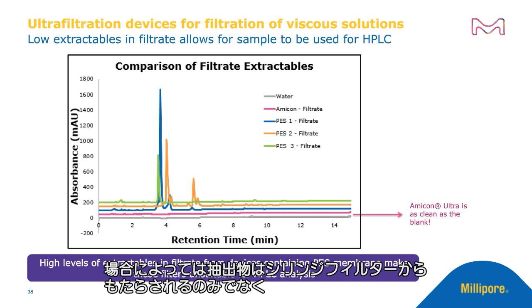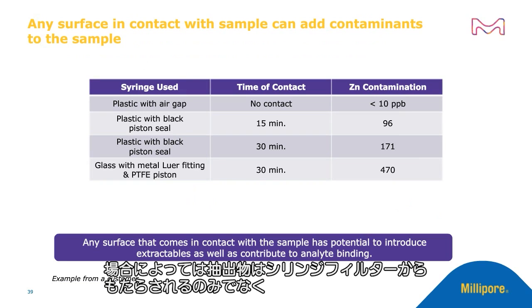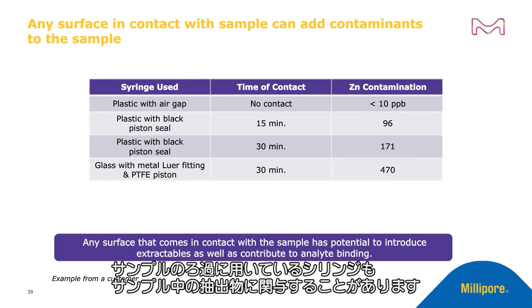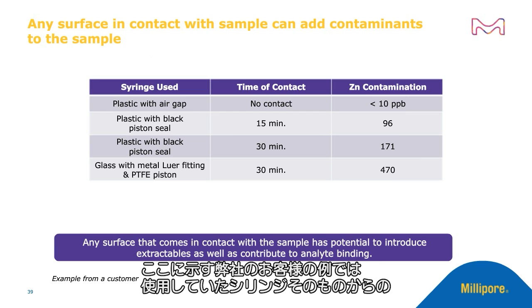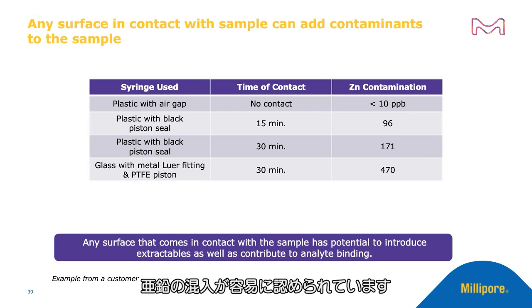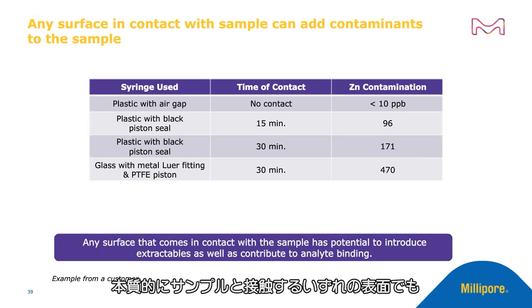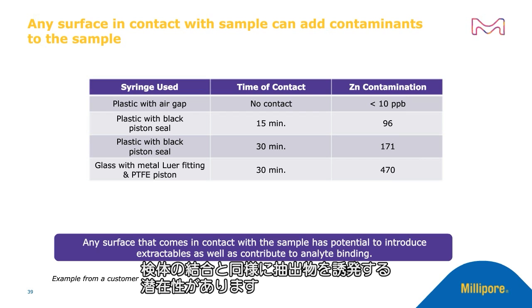Sometimes the extractables are not only from syringe filters, but even the syringes that we use for filtration of sample can contribute to extractables in the sample. This is an example from one of our customers where zinc contamination could be easily observed from the syringes themselves that the customer was using. In essence, any surface that comes in contact with the sample has potential to introduce extractables as well as contribute to analyte binding.